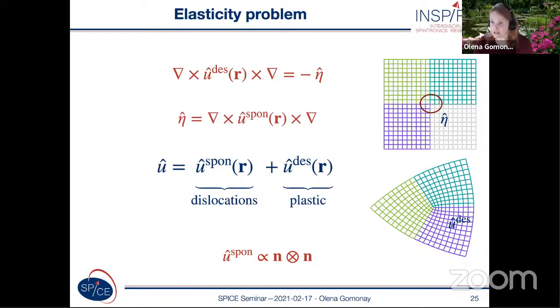And in elasticity theory, this concept of incompatibility is used when people try to describe what happens in materials with such structural defects as disclinations, shown in the figure, or dislocations. The incompatibility created by these types of defects is the source of additional strains in the sample, which try to relax this incompatibility. These strains are usually called plastic strains.